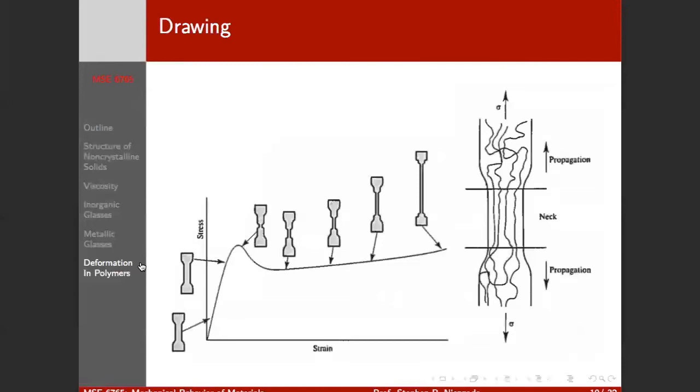if you take a six pack ring or pop bottle, and you cut a little segment out of that. You can just pull it by hand. If you pull it slowly, you can draw a couple inch piece out to a fairly long distance, and it's really strong in the tensile direction. But if you grab it in the transverse direction, now you're only pulling against these London forces. You give it a little tug, and it just falls apart into a bunch of individual strands. It's sort of a fun thing to do.